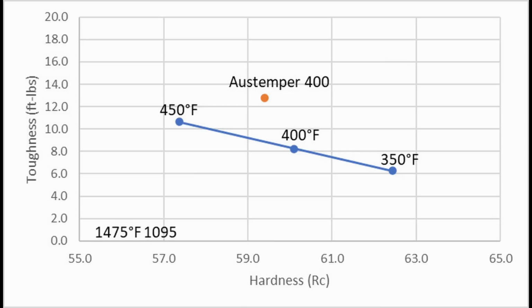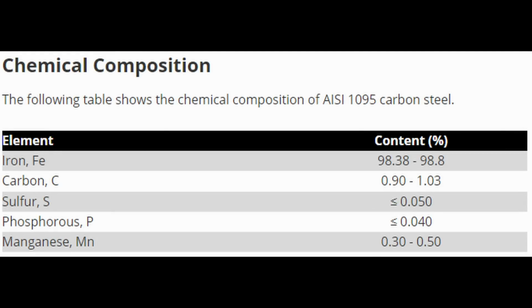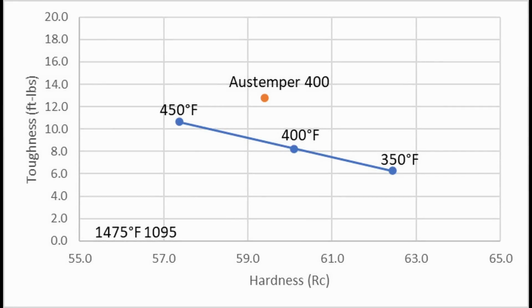One possibility is cleanliness of the steel. So there are certain impurity elements found in steel. Two common ones are phosphorus and sulfur. So for example, if the phosphorus and sulfur content was high in this 1095, that could be reducing the toughness. Because we are replacing potentially brittle martensite with tougher bainite, but if there are other things that are reducing the toughness, such as a high content of large carbides or a high content of impurities, those are going to be reducing the toughness regardless of what we do to the matrix, changing that from tempered martensite to bainite. And so something else in this 1095 is limiting the toughness, and I'm not sure what it is.